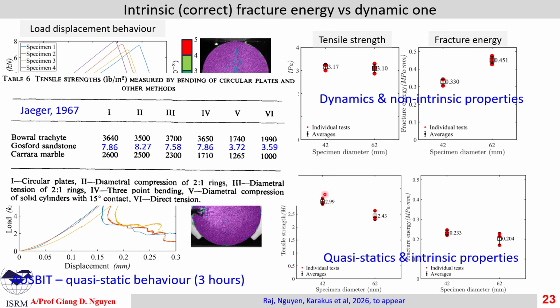And we can have a brief idea of the tensile strength here on Gosford sandstone, the sandstone used in this test. A long time ago we got this paper, and the direct tensile strength in this case is 3.59, which is close enough to what we got here. The difference could be the inhomogeneity of the material, and this still needs a bit more investigation.